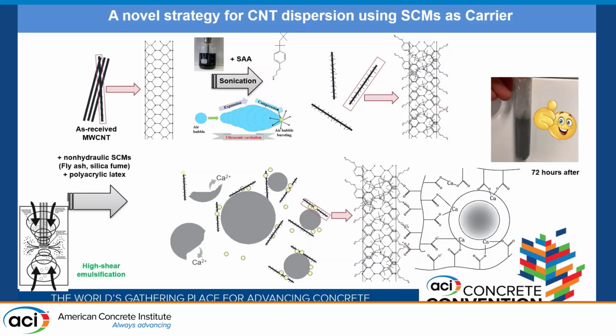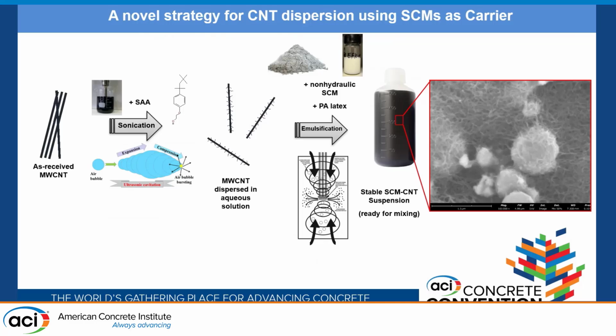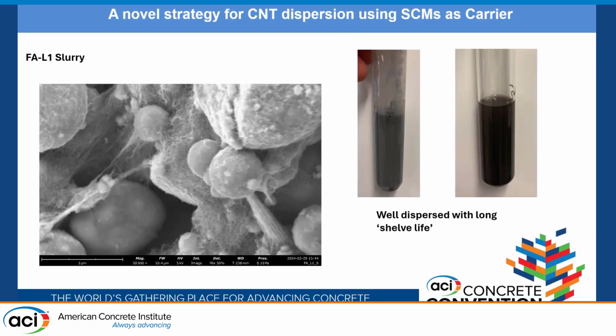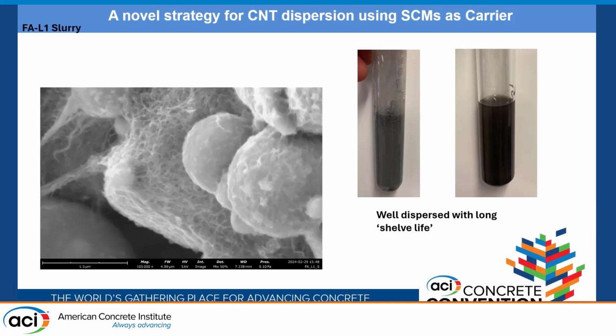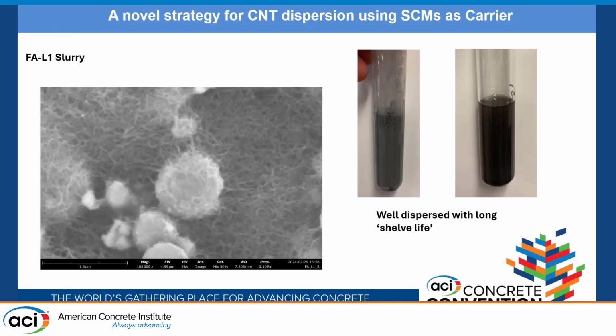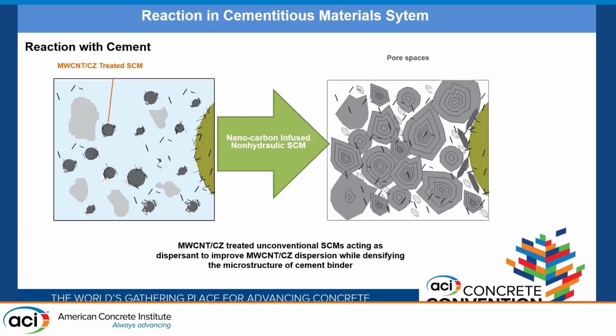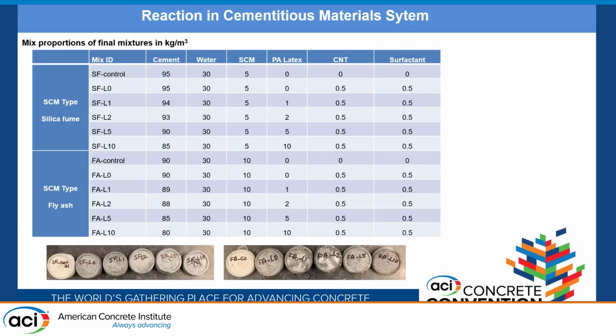And finally, we started getting stable suspensions. Even after about 3 days sitting there, it doesn't separate anymore. So we further took that under the SEM, trying to look at it, and the nanotubes started to coat the SCM surfaces. Those are just more pictures showing, in that process, how it started wrapping around all the SCM particles. And then we started experimenting with delivering that by just mixing with cement paste. The hope is that because the suspension carries the SCM, which is used as a carrier to deliver the nanostructured carbon in the cementitious system, it will help with the dispersion in the hydration process.